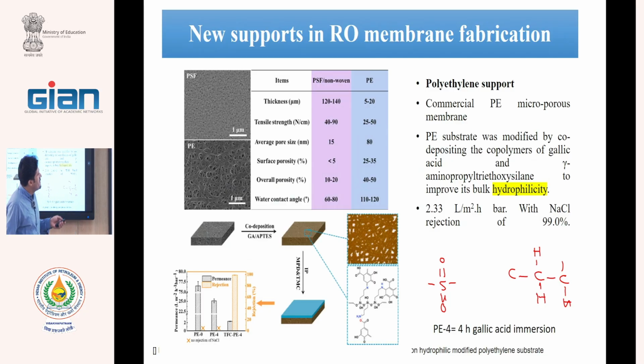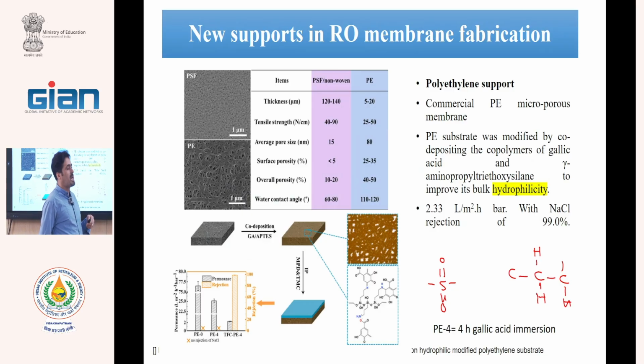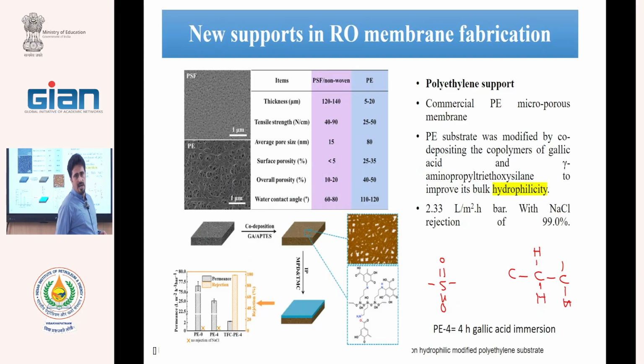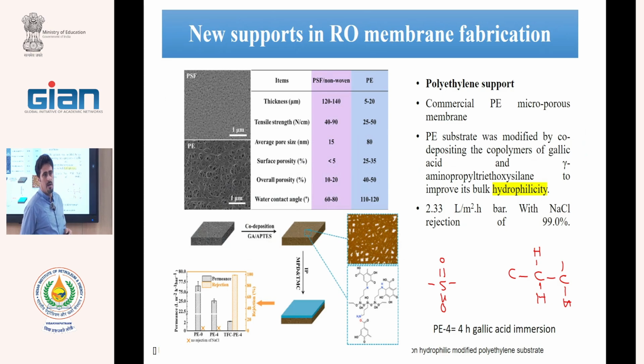In this case, before using the polyethylene support, we must increase the hydrophilicity. For increasing hydrophilicity, many methods are used, such as chemical reactions, oxidizing with permanganate, oxidizing with hydrogen peroxide. But the most used method on industrial scale is plasma methods. Plasma is a gas medium that has many radicals and can easily oxidize everything because they are very, very active radicals.